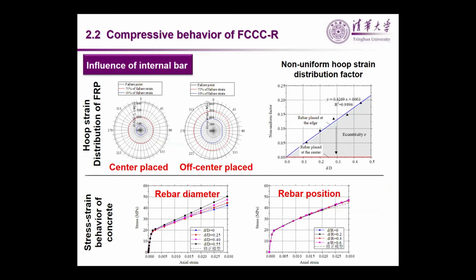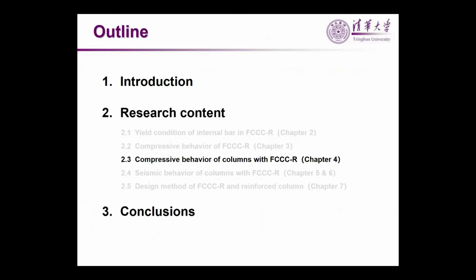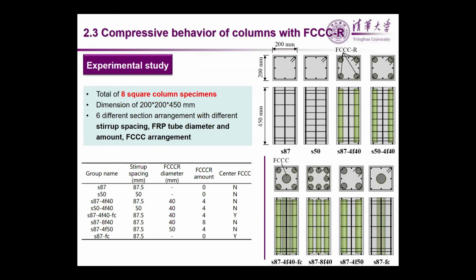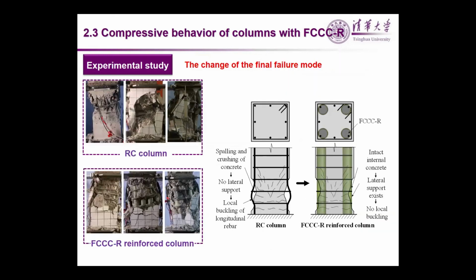Well, in chapter 4, the compressive behavior of the columns with FCCC-R is studied. Eight FCCC-R reinforced columns were tested under cyclic axial compressive load. And the main parameters include the amount and diameter of the FRP tube, as well as the stirrup spacing. But test results indicate that the existence of the FCCC-R will change the final failure mode of the column. During the test, the local buckling of the vertical bars, rupture of the steel hoops and crushing of the core concrete were not observed. But it is noticed that the overall buckling of the FCCC-R has become a critical issue and shows obvious influence on the compressive performance of the column.